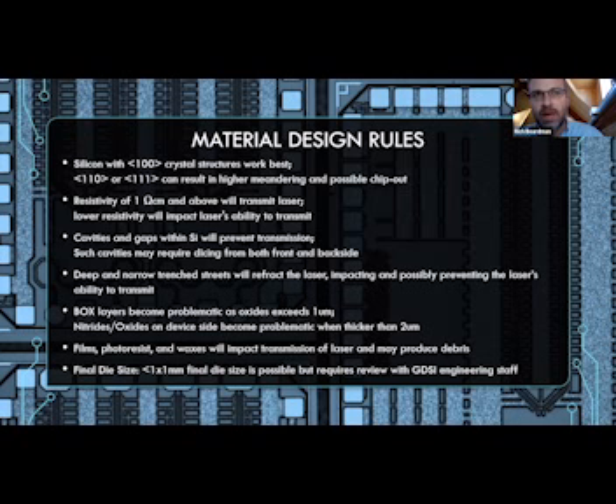So a lot of customers will give full thickness wafers for this process. So then we're into the orders of magnitude of 700 or 800 micron thick. So if we extrapolate out on the math, we're looking at asking for streets that could be up to 320 microns wide, and that's pretty wide and not always able to be offered.